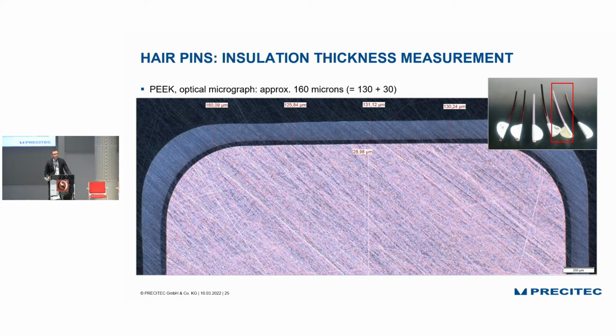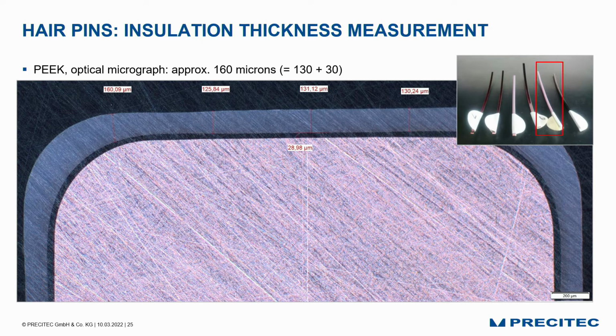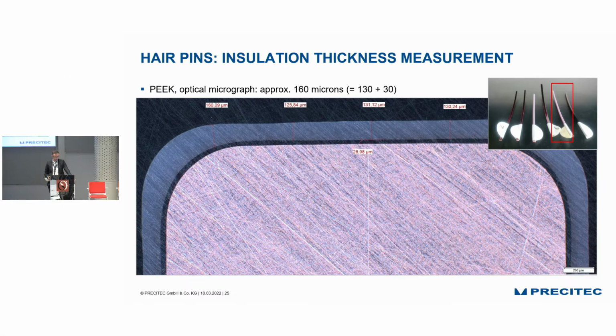Another example, which is frequently asked, is in the field of stator production. Here, customers want to know about the thickness of the insulation layer. They use this information to adapt the following not stripping process, but afterwards the bending process. If they know the thickness, they adapt their bending process of the pins. And here we made a cross-section of one of these different 6 pins, where we ended up at a total thickness of 130 microns plus 30 microns, so 160 microns in total of this insulation layer.